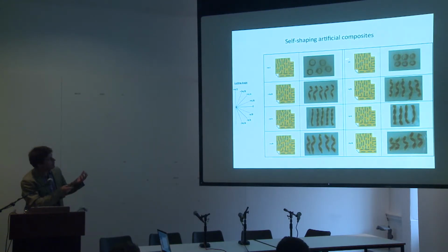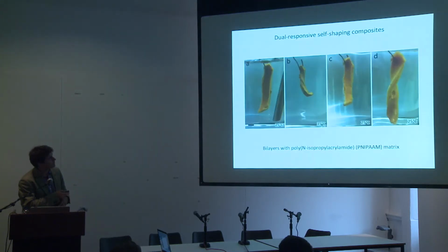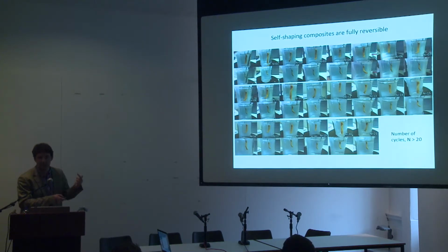And you can then go all the way from pure bending to pure twisting with mixes of the two, and change the chirality depending on the relative angle of the two, and that provides a wider design space for these self-shaping structures. The other interesting thing is that we can pick polymer matrices which are responsive to more than one stimulus. For example, this one would be responsive to water uptake and temperature, so that if you first increase the temperature, it twists in one direction, and then if you cool it down again and let it swell, it would twist in the other direction. And you can repeat this as much as 20 times, and it will always do it reproducibly.